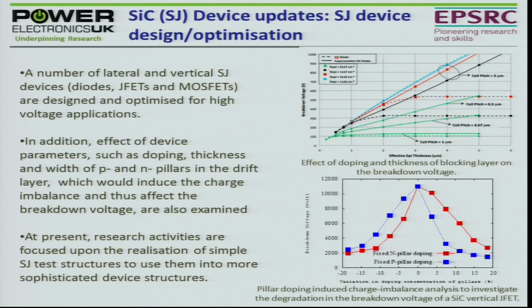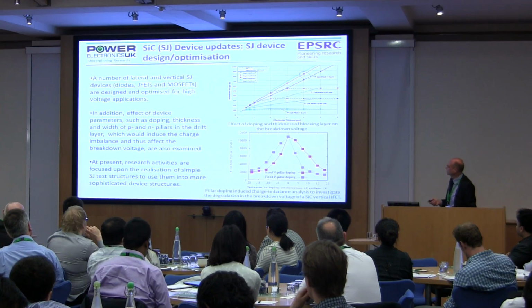This shows some more simulations of the superjunction devices and how important it is to get the doping in the P columns and the N columns as close to each other as physically possible. Otherwise, the blocking voltage falls off very quickly. This is where it's balanced in the middle, so the charge in both those pillars is the same. If it falls one way, you can see that the blocking voltage falls off very quickly, and if you get it the other way, it falls off very, very quickly. And that's part of the challenge in making these devices.